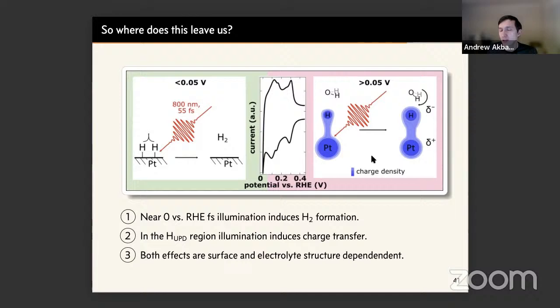Okay, we have a comment in the chat that I can read out, and maybe at that point we will end. If you want to comment too, you can do it. So the comment is the following: just in case, at potentials less than 50 millivolt versus RHE, a lot of H2 is formed even without illumination. So there are no gas bubbles, just dissolved molecular hydrogen. The quantity of this hydrogen depends on the time of the potentiostatic treatment or experiment, and the formation of molecular hydrogen will continue up to the point when we reach equilibrium pressure inside the electrolyte.